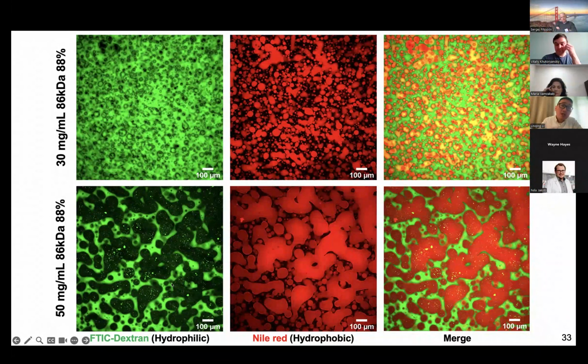You can see now you have completely separated the two domains, where you have the highly cross-linked density hydrophobic domains interspersed by the relatively lower cross-linking regions, which is the hydrophilic side, which is now showing you two completely separate areas at 50 mg per ml, and these data confirm the observations we saw in our